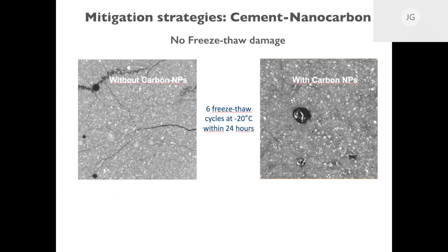How would the presence of filler inert particles in different sizes modify these results, such as limestone or fly ash? Yes. So at the moment, the carbon nanoparticles are also, in a way, a filler in the material. They're filling up the pores, so the less porosity, the less water can go in. So probably different types of fillers also have such an effect, but it depends if these fillers are hydrophilic or hydrophobic. And more specifically, we are in the process of upscaling this material, so we are making a mortar out of it. There we will investigate all these different types of fillers.